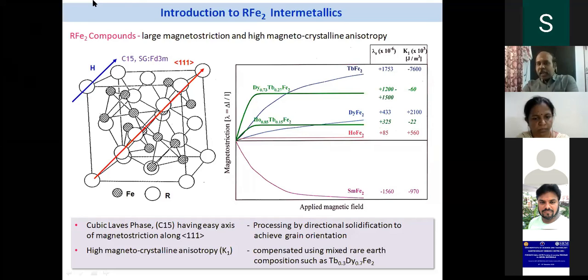The right side figure shows how the magnetostriction of different magnetic materials varies with respect to an applied magnetic field. As I told you earlier, the first classic material which was discovered was terbium iron, TbFe2, which shows a high magnetostriction of 1753. But if you see the magnetic field requirement, it is relatively high. That means you get such a high value only at high magnetic field. To generate such a high magnetic field, we require a very big magnet, and your final device becomes very bulky, so it cannot be used in a practical way.